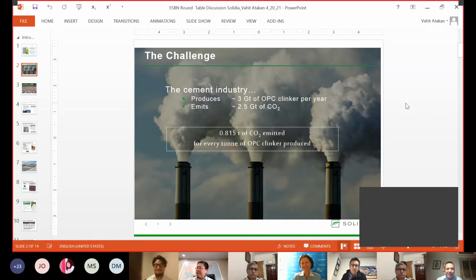Yeah. Okay, all right. So in this one, I'd like to define the challenge a little bit. The cement industry produces about 3 gigatons of OPC clinker per year, and it emits about 2.5 gigatons of CO2, which is a significant number. As a basis, I'm taking the OPC clinker production in a modern kiln. So we are talking about 0.8 tons of CO2 emitted per ton of OPC clinker produced. The reason we are using clinker instead of cement is that different countries have different regulations and use different levels of clinker factor. So to make the calculation simple, we use this number as a reference.